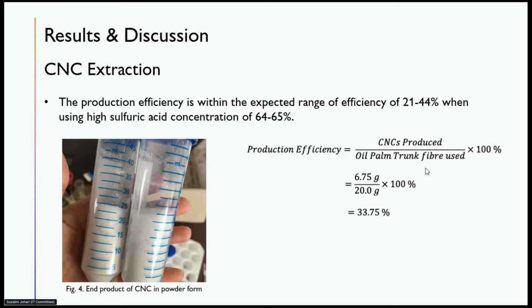Figure 4 shows the end product of the CNC powder form that is ready to use. So the production efficiency of this extracted CNC is about 33.75%, which is within the range of expected efficiency when we are using high sulfuric acid concentration. When strong acid is used, the yield is usually lower because the content is purer. This is because the sulfuric acid will attack the amorphous region of the fiber, leaving only the pure crystalline region. And this method is still the most commonly used treatment today, even though the yield is lower compared to other treatment options. Next slide.